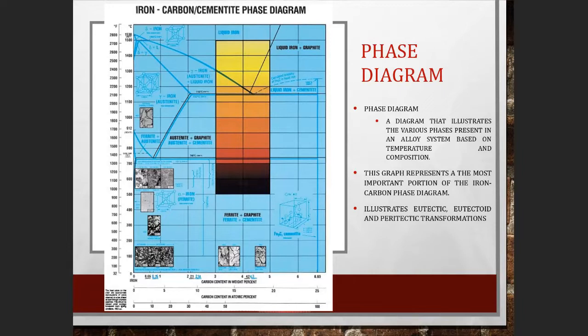This particular diagram, let me pull up a, let's see, do red. This particular graph here shows three different types of transformations that occur. The first one is up here in the top left corner, and that is called a peritectic transformation. In that transformation, you are going from a liquid plus a solid 1 phase, and it's going to transform to a completely different solid.